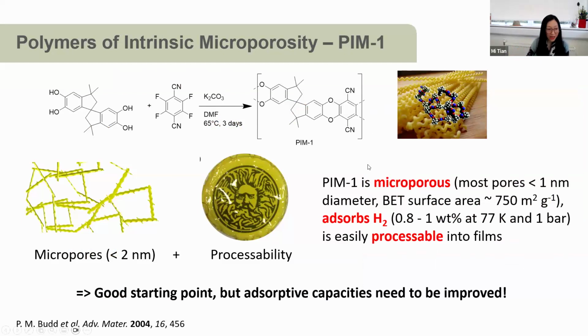So PIM1 is a microporous material. Most of the pores are less than 1 nanometer, and that is the ideal pore size range for hydrogen storage. It can absorb hydrogen about 0.8 to 1%, which is not really ideal, but okay. The most important property of PIM1 is it can be processed into membranes, transparent yellow membranes. So this is a very good starting point. But the porosity is low. Hydrogen storage capacity needs to be improved.